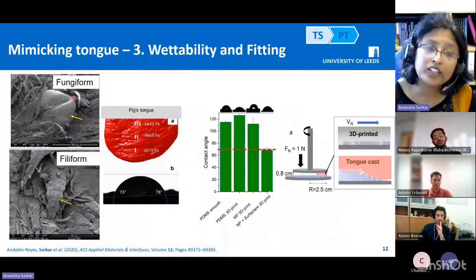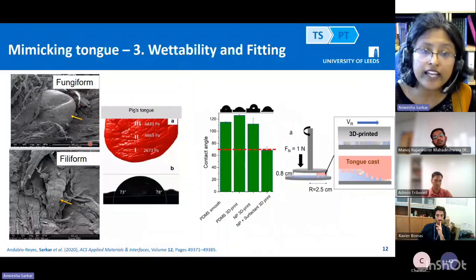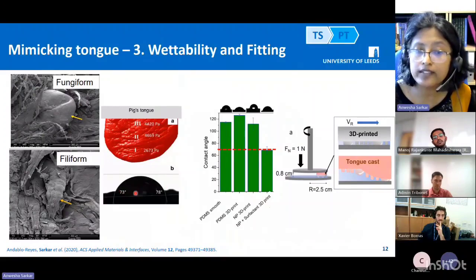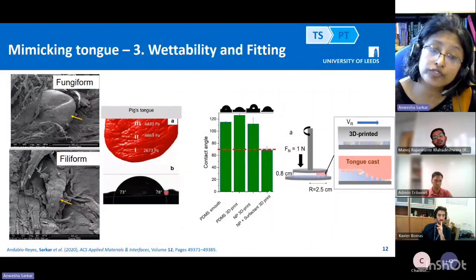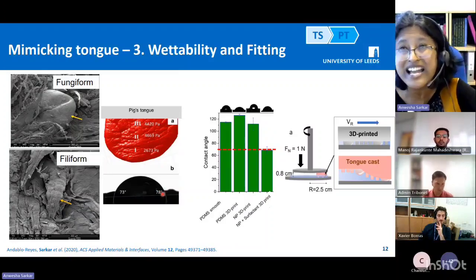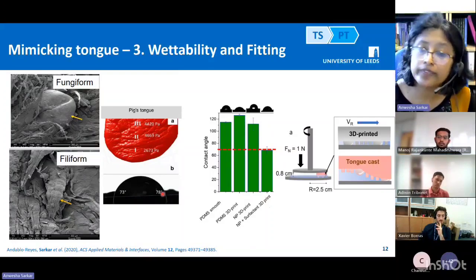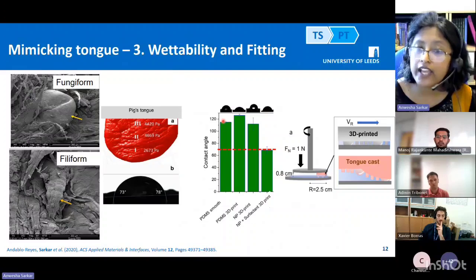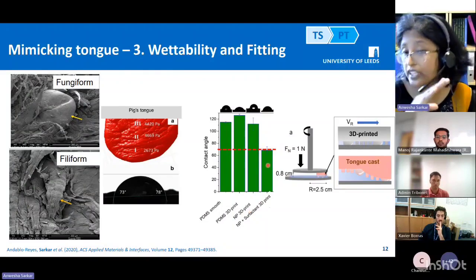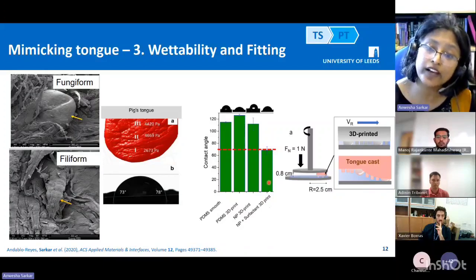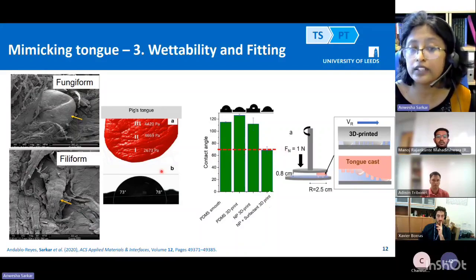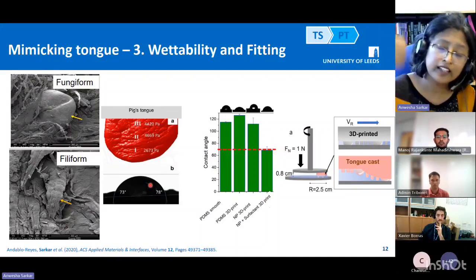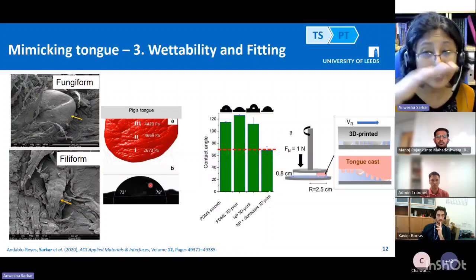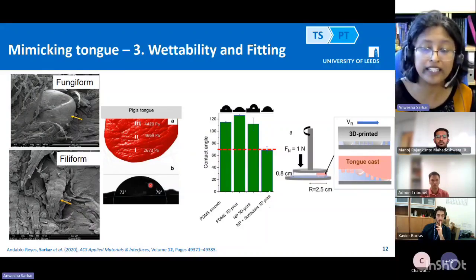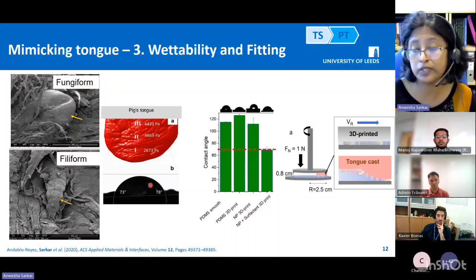So we again went back to the pig's tongue, and we identified that the static contact angle was in the order of 70 degrees. So it's not really hydrophilic, but it's also not hydrophobic. If you look at PDMS again, you have a very, very high hydrophobicity. However, with the new polymer, EcoFlex, we added the surfactant. In the beginning I said I will get back to you on that. So we added the surfactant to make the contact angle similar to a real human tongue. So we have created a soft surface. We have made it rough with the right kind of size, shape, and distribution of papillae. And third, we have made it wettable, similar to a real human tongue or a pig's tongue.